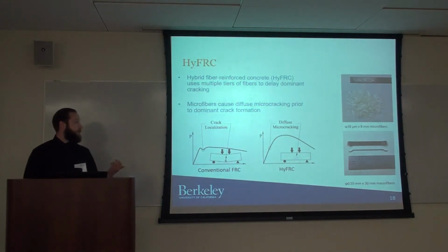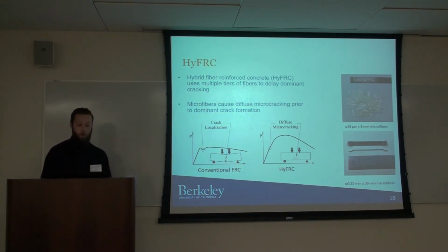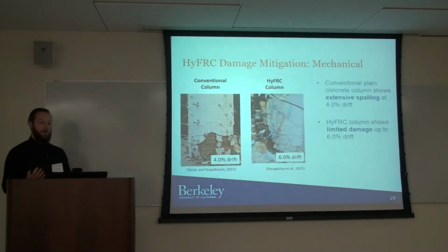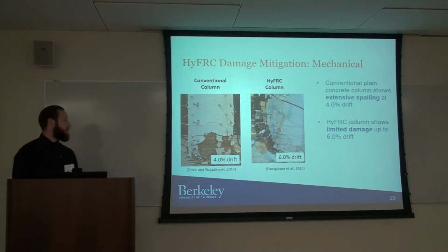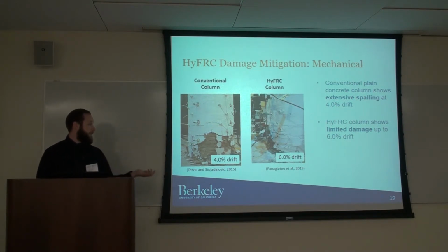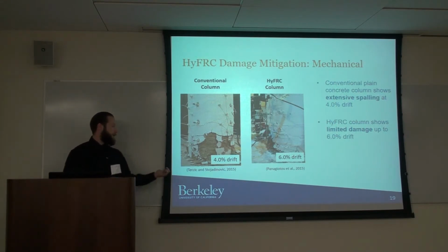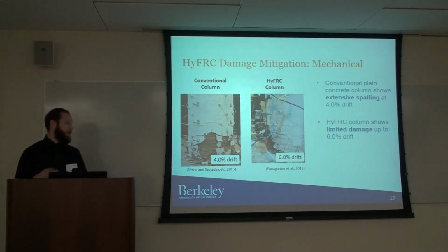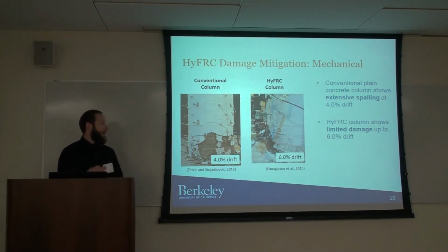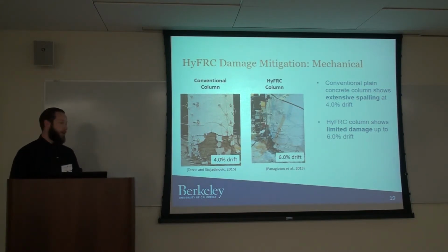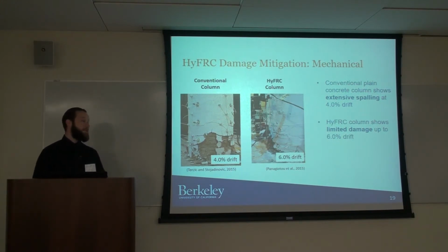So as you can see in this case, the fiber combination that we utilize allows us to achieve diffuse microcracking, and that allows the material to achieve strain hardening and deflection hardening behavior, which has been shown in bridge columns to increase the toughness of structures. In the first test here, this is a conventional concrete column by Vesna and Boja at UC-Berkeley, and that can be compared with this test by Marios as well as other collaborators. And the HyFRC column had significantly improved performance, up to 50% higher drift, and they were similar columns in plan, with the main difference being the type of material used, specifically hybrid fiber reinforced concrete versus conventional concrete.